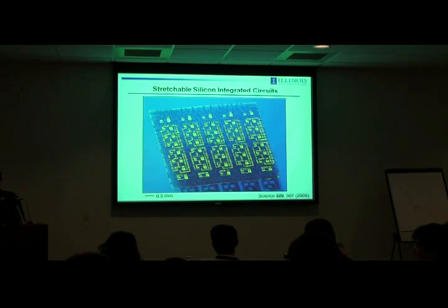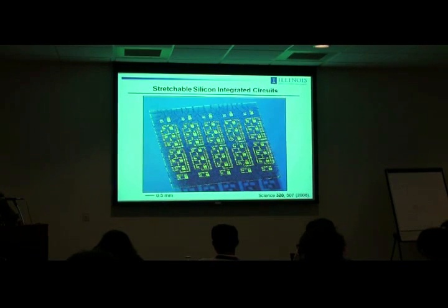Does it have good adhesion with the silicon? Yeah, so polyimide is used in packaging applications currently in the silicon industry, and in some cases it's used as an interlayer dielectric. So in that case and others, we're usually trying to select polymer materials that have already had some validated range of applications in existing conventional silicon ICs. And so those kinds of problems have been worked out for us, and we try to just build on that and exploit it. Any questions?